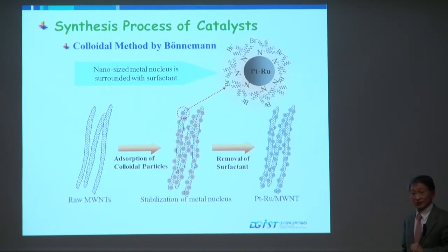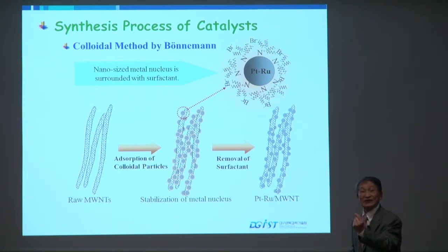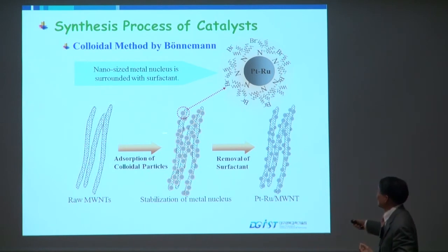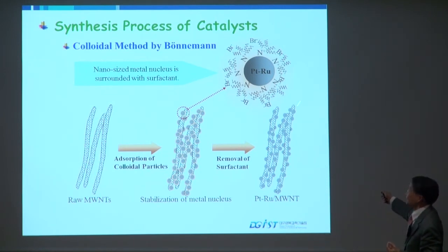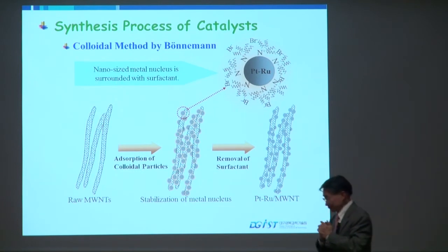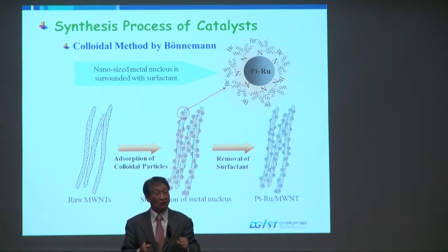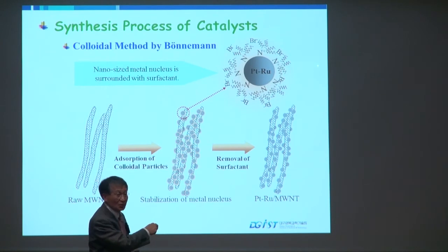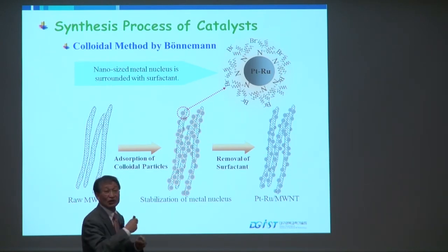So chemical deposition, electrochemical deposition part. Generally, what you do for preparation of catalyst is, I have prepared this with the Bönnemann process, which is colloidal reactions. You start with nanotubes, and since the nanotube is not very sticky for metal ion adsorption, you introduce these colloid spheres of the catalyst. It is either platinum or platinum alloy, or platinum ruthenium alloys.